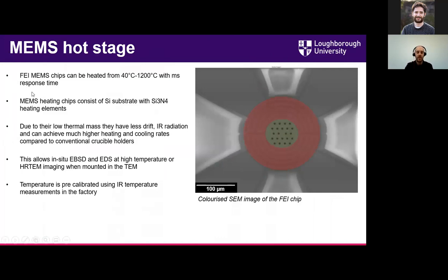Not just the FEI chips, but pretty much all the chips on the market use a similar technology of a silicon substrate with silicon nitride heaters, and they all have essentially the same advantages in that they can be heated from around 40 degrees C up to around 1,200 degrees C with millisecond response times, so that they can heat very, very quickly. And they have a relatively low thermal mass. This means that they typically have less drift, they give out less infrared radiation, and so they can achieve high heating rates while also allowing you to perform EBSD and EDS in situ.